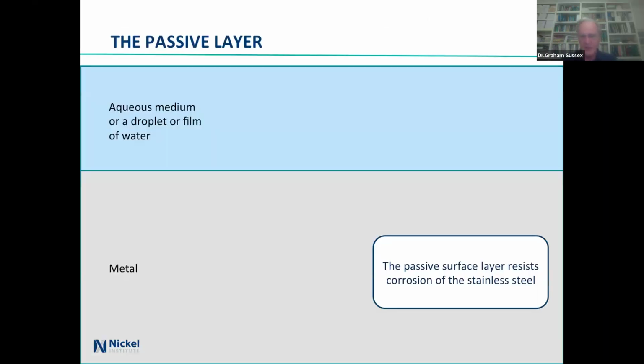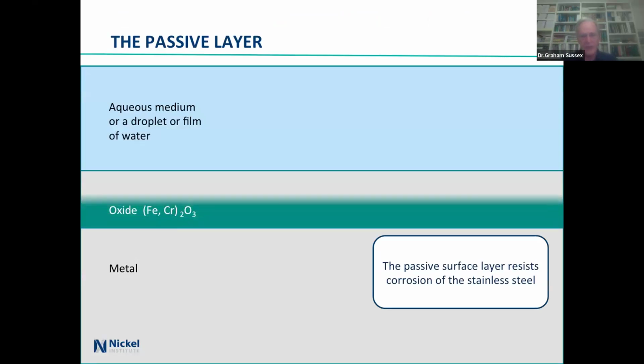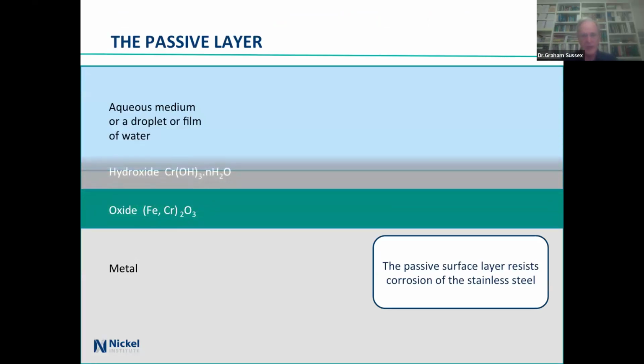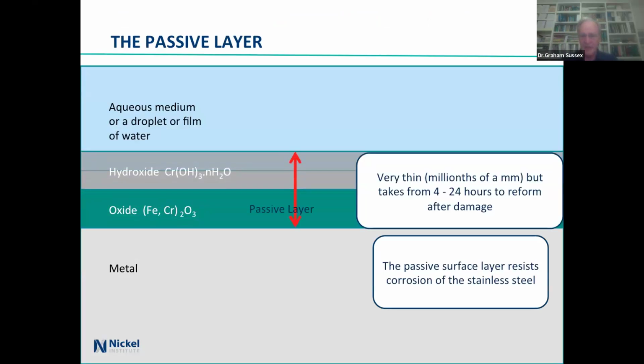So, stainless steels, passive layer forms, you get moisture in the air, oxygen, nice thin layer, passive, and it's millionths of a millimetre thick, but it takes somewhere between 4 and 24 hours to reform. It doesn't happen instantly, so if you carefully brush the surface up and then put it into service immediately, you don't expect to get absolutely top-rate quality out of it.